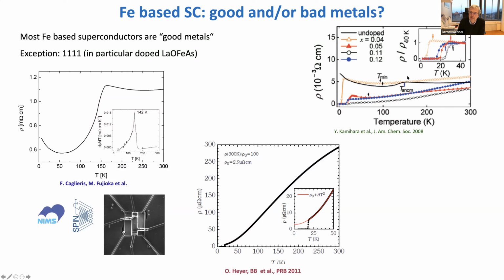This is the first report on superconductivity in these materials, and there you already see that you're basically dealing with something which is very close to localization, very close to insulating behavior. And the smallest resistivity which I found so far was one measured in a small single crystal here. You still see, if you look at the absolute values, this is far away from being a nice metal. And you see here this typical phase transition. Above the phase transition, there's this increase, this tendency to localization. But the main message you can take from such a figure is that there is a strong decrease of the resistivity when you go through the transition.